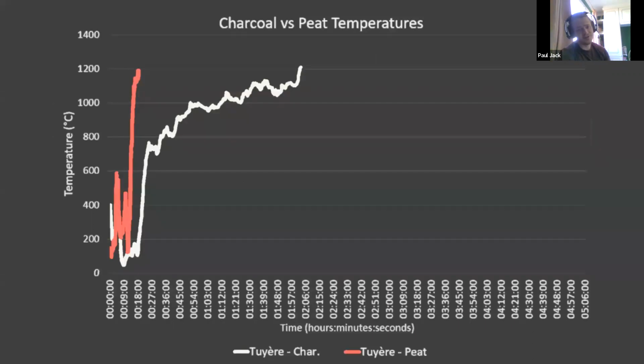these are the temperatures recorded from some thermocouples, that is to say, some fancy thermometers, inserted through the tuyere. So what that means is that these thermocouples were placed through the area that we were bellowing into, sort of a little hole into the furnace. That lets the air be forced inwards. And so in theory, this is the hottest part of the furnace, the formation chamber, as it's often called, where the iron actually becomes an iron mass.